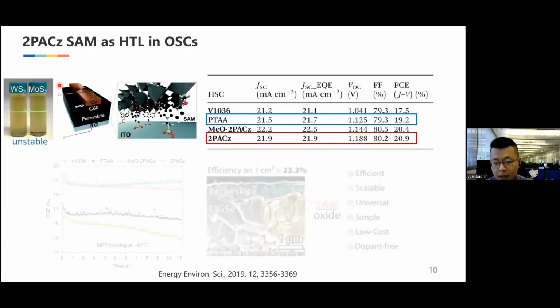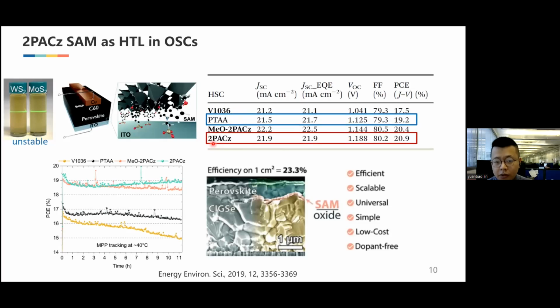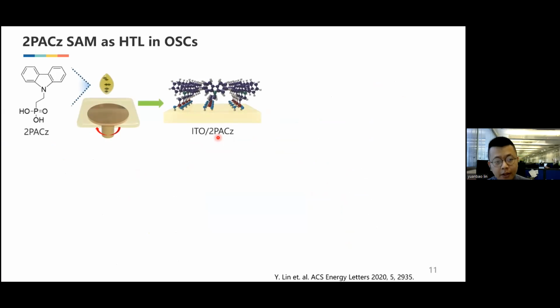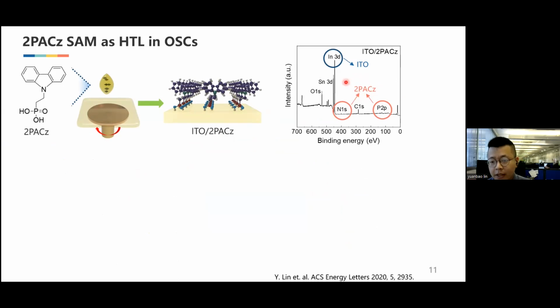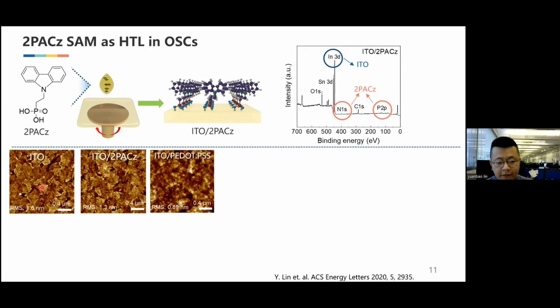And in 2019, in perovskite solar cells, the 2PACz SAM was synthesized and used to replace PTAA. This 2PACz SAM has better performance and better stability as compared to PTAA. So we tried to use this 2PACz SAM in the OPV, and we spin coated the 2PACz SAM on the ITO, and we used XPS. We can detect the 2PACz on the ITO, but due to the thin layer of the 2PACz on ITO, we can detect a high ITO signal also. But from AFM, we can't see any difference after spin coating the 2PACz on the ITO. This is because of the thin layer of this material.